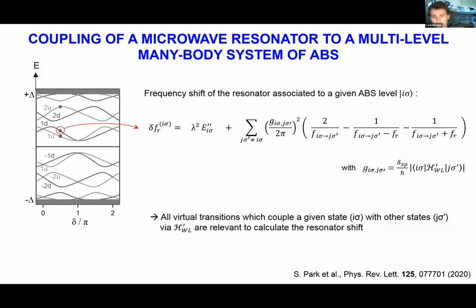So the main message of our work is encoded in this equation that Sumun already presented, and it gives you the frequency shift of the resonator associated to a given Andreev bound state I sigma. So for example, if the level 1 down here is occupied, it would contribute to shifting the resonator first by its intrinsic curvature, so the second derivative of the level's energy with respect to the phase, and also because of all possible virtual transitions between these states, 1 down and the others, so 2 down, 2 up, etc. So these virtual transitions involve emission and absorption of photons with the resonator.